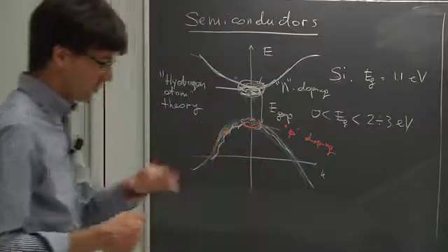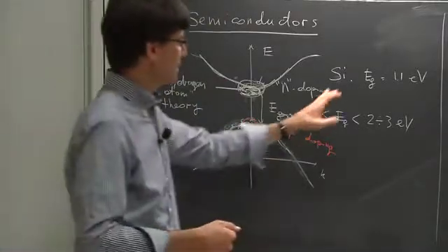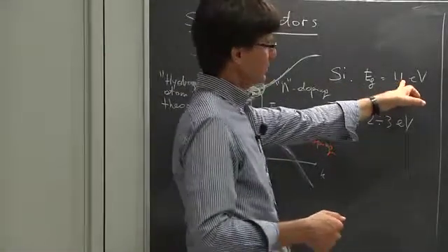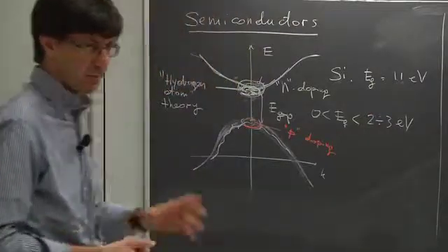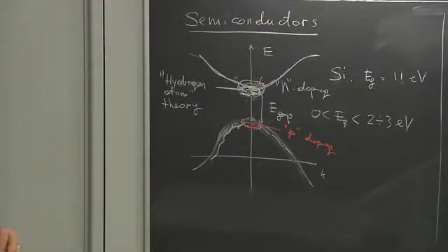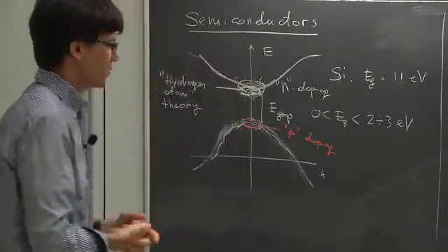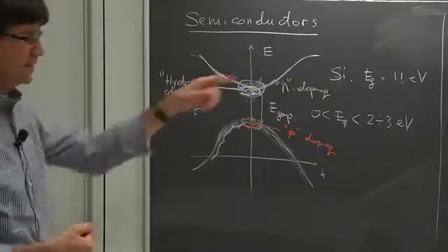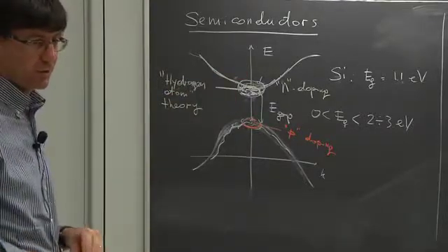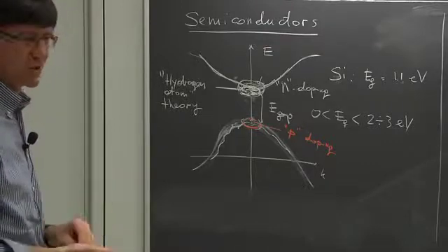If you go from 0 to 300 Kelvin, for example, the band gap of silicon changes by, well, one significant digit, 0.1 electron volts, roughly, order of magnitude. So the change is due to temperature. Just the renormalization due to the temperature is larger than the effects due to the perturbation potential of the impurity. So the band gap doesn't really change too much.